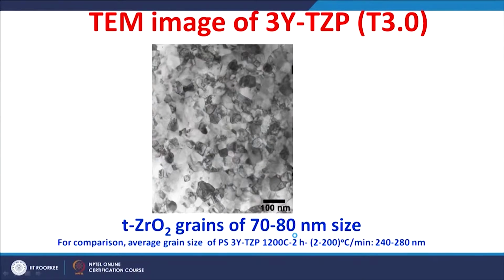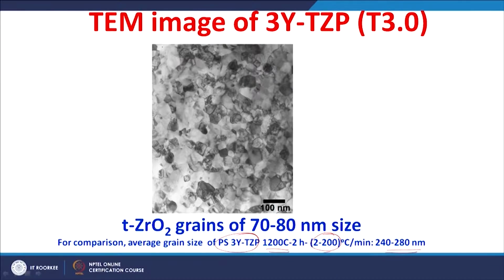This is the typical TEM image of this 3% yttria stabilized tetragonal zirconia. You can see all these grains of around 70 to 80 nanometers, and for comparison, it is to be noted that the average grain size of the pressureless sintered 3% yttria stabilized tetragonal zirconia polycrystalline, sintered at 1200 centigrade for 2 hours, was around 240 to 280 nanometers. So, you have the benefit of restricted grain growth when these ceramics are prepared by spark plasma sintering. In spark plasma sintering the heating rates were also high, at around 600 Kelvin per minute, whereas the pressureless sintering was done at lower heating rates.